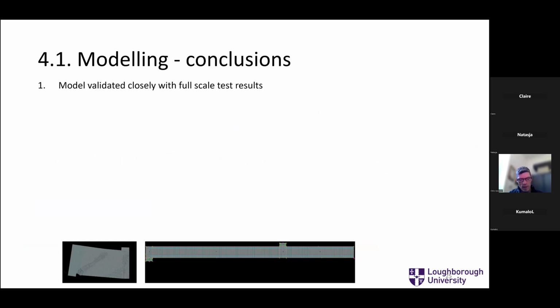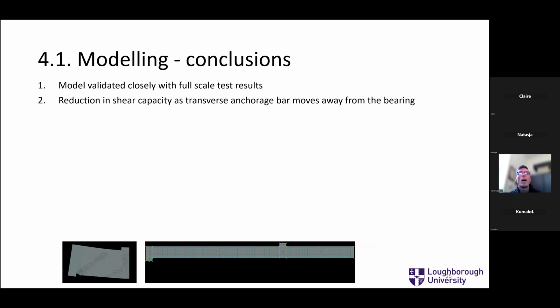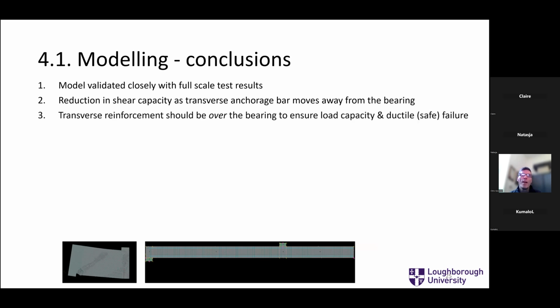So we concluded the modelling was a good model. It validated with the full-scale results. You got a reduction in the shear capacity as the bar moves away. So that's the critical thing to find. And also that's the thing that's very hard to find. You can't just do it from visual inspection. And therefore, this rebar should be over the bearing to ensure your load capacity. And if that transverse reinforcement is over the bearing and you put a high load on it, you'll get a ductile failure, which is a safe failure. The more that bar moves away, the more likely you are to get a brittle shear failure without any warning.